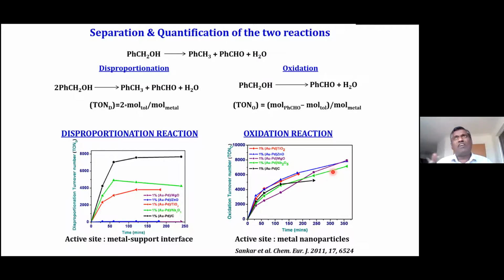So we can conclude that the metallic sites are responsible for the oxidation reaction, whereas the metal support interfacial site is responsible for the disproportionation reaction. When we know the active site is the metal support interface, we can tune that active site by changing the support. By changing the support, we are changing the metal support interface, and that changes the activity for this disproportionation reaction. And consequently, we can tune the selectivity for this reaction.